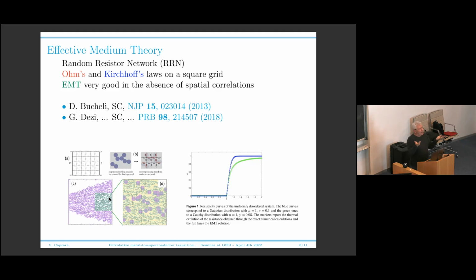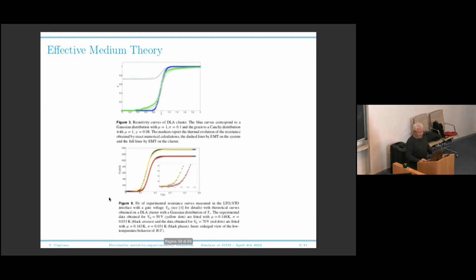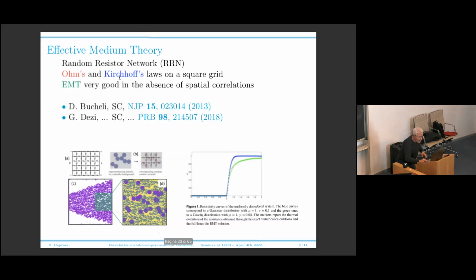What do you think now will be the comparison between effective medium and the exact solution of the random resistor network? Very bad. If you compare the two, now this is effective medium. Of course, since the fractal is very sparse, you are very far from the percolation threshold, very far. So effective medium will fail to give you a percolation, because if you were to distribute those links in a totally random way across your system, then you would be very far from percolation. But as you see, those filaments do percolate because they were produced by a diffusion limited aggregation. So by definition, they percolate. They go from one end of the system to the other.